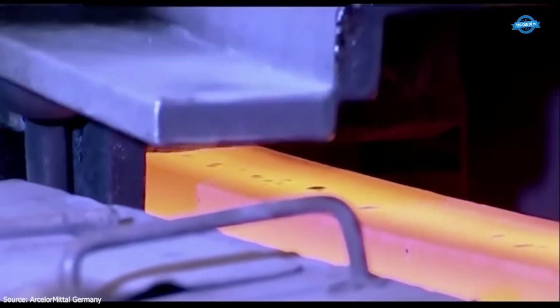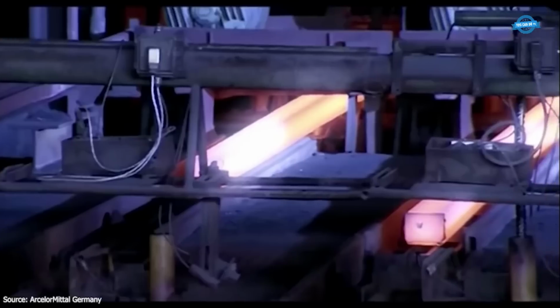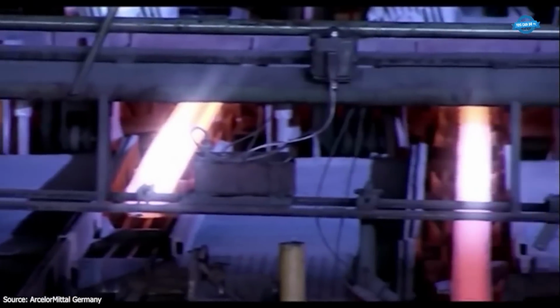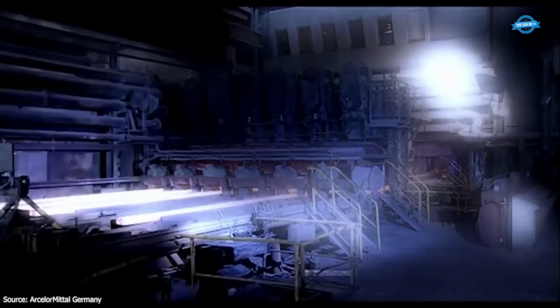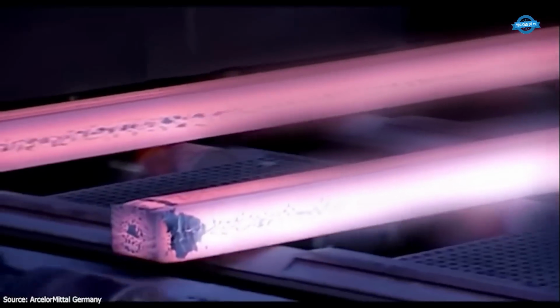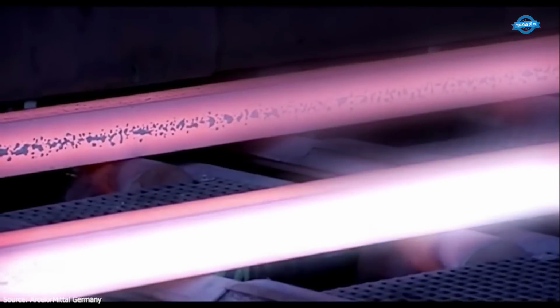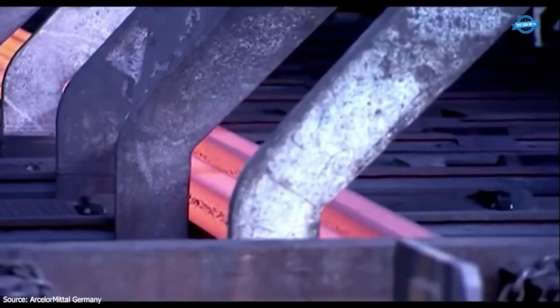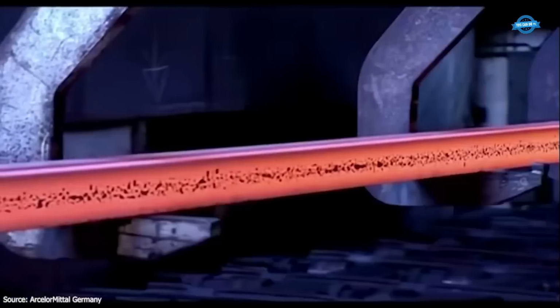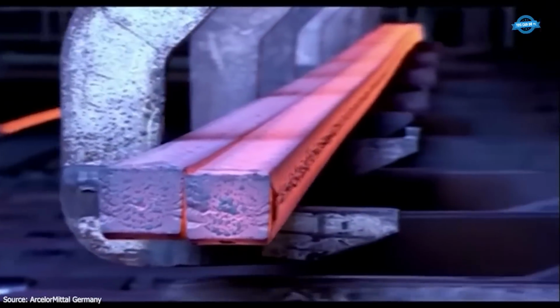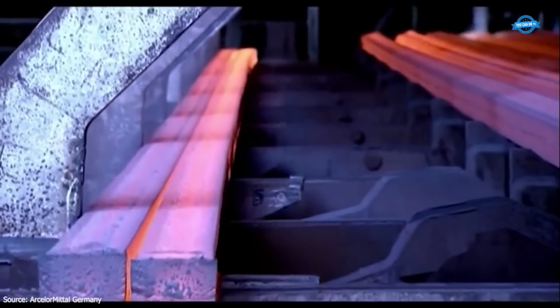The EAF at Hamburg consumes about 600 million kilowatt-hours of electricity annually. Graphite electrodes, capable of carrying up to 75,000 amperes, introduce intense electric arcs to melt the charge. The molten steel reaches temperatures around 1,630 degrees Celsius. A foaming slag forms during melting, which protects furnace walls from thermal stress.